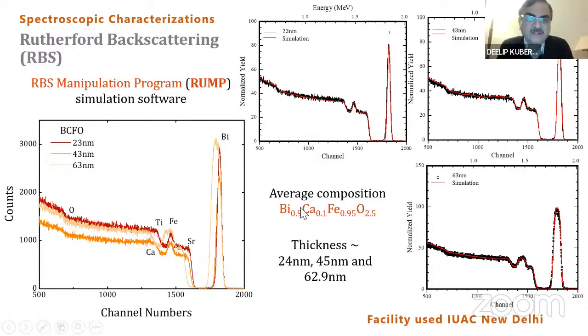And the average composition of our film was bismuth 0.9, calcium 0.1, Fe 0.95, O 2.5. You can find out all this composition by analyzing the data also, and the thickness was again confirmed. The thickness which you measured using XRR was confirmed to be 24 nanometers, 45 and 62.9. Instead of 63, we got 62.9. So almost whatever the XRR measurements gave was confirmed using Rutherford backscattering. This is the second confirmation of our thickness of the films.